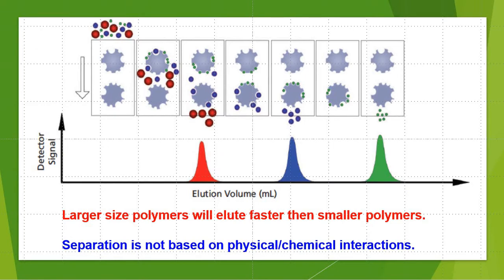Like I stated previously, GPC works by separating polymers based off their hydrodynamic size. This separation occurs by passing a sample through a GPC column, which is filled with a porous packing material. At the top here is a sample of polymers that are represented by different size spheres. As the polymers pass through the column, large polymers are only able to go through the largest size pores within the system. And as a result, they're able to pass through the column relatively quickly.